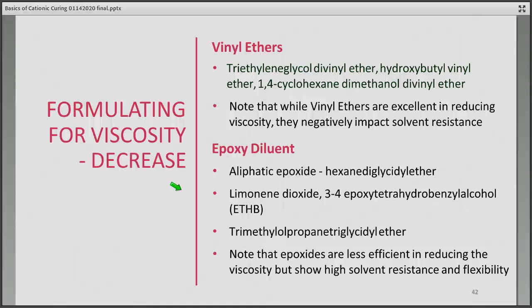If you want to formulate for a viscosity decrease, say you want to lower your viscosity because of your coating system, there are multiple ways you can do that. You can add the vinyl ether. These tend to be very low viscosity systems, and I have a few listed up there that have been used in the past. Now these vinyl ethers are excellent in reducing viscosity, so they're great diluents. However, they do tend to negatively impact the solvent resistance of your formulation, so you have to balance that property out, depending on what you want to achieve.